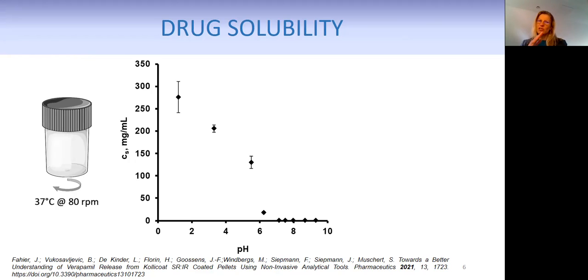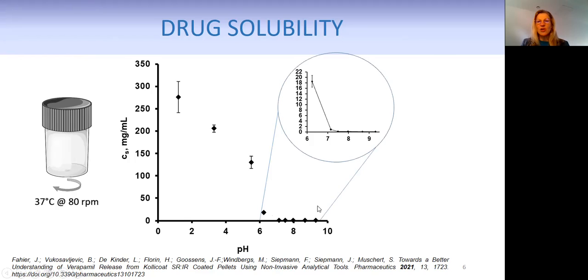And you can see actually that the drug solubility is dropping with increasing pH. And if you take a closer look at the region between 6 and 9.5, you can see that there is a severe drop in drug solubility.